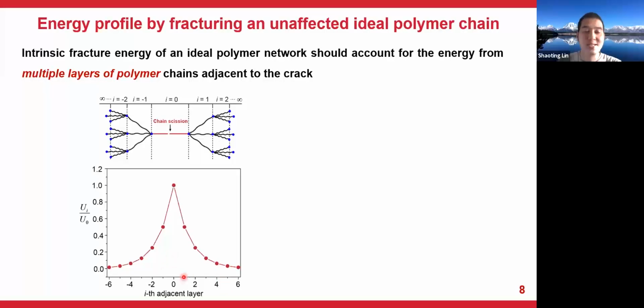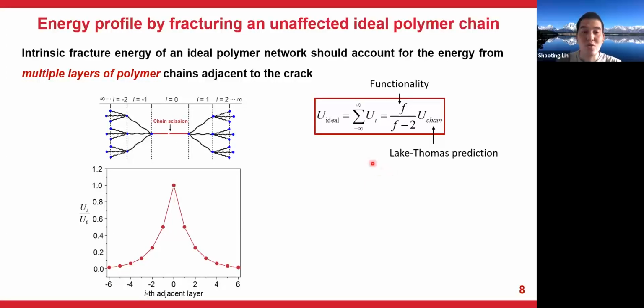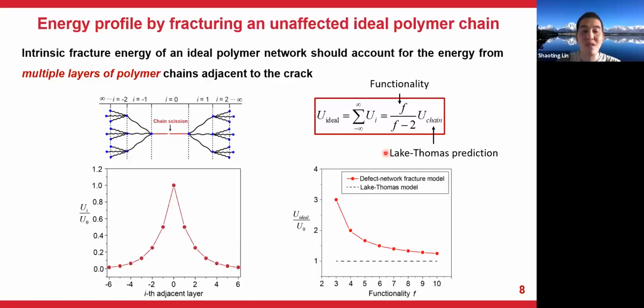And qualitatively, this is consistent with the recent experimental observation based on mechanochemistry published by Professor Craig. And we further calculate the energy relaxed by all the layers. So here is the expression, which eventually gives a finite value with a prefactor of f divided by f minus 2, where f is the functionality of the polymer network. Here U chain denotes the pristine value based on the Lake-Thomas prediction. And the energy contribution by the neighboring chains can be significant, especially for ideal polymer networks with low functionalities. So for example, for a tetra-arm ideal network with functionality of 4, the intrinsic fracture energy predicted by our model is 2 times the Lake-Thomas model's prediction.